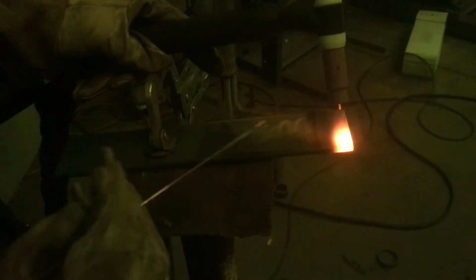You'll get a little bit of oxide that you have to grind off if you want to tie back into that bead. And you have to hover the TIG torch over the edge so it maintains the gas shielding while the metal cools, or else you get a bunch of oxides forming on the top of it. As you can see, that little heat line off the beads is about an inch away from it there. And that right there tells me it's getting a little bit hotter than I'm wanting it to.